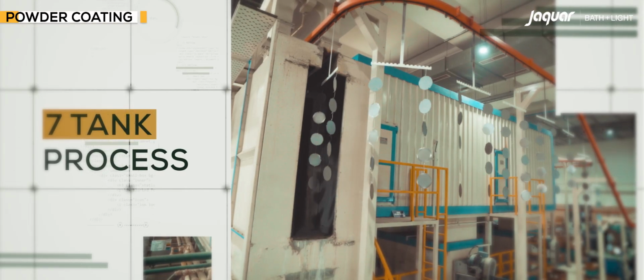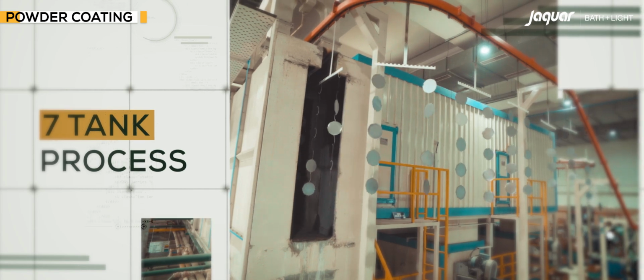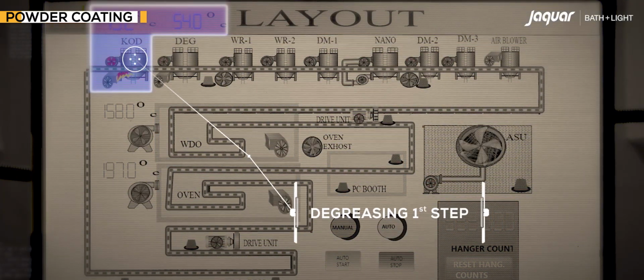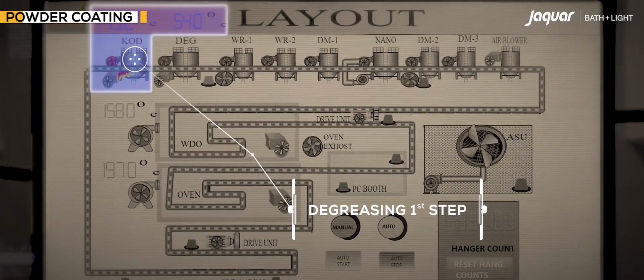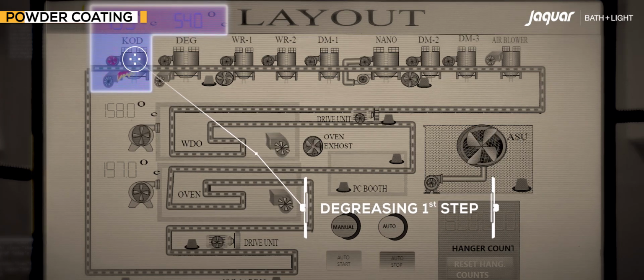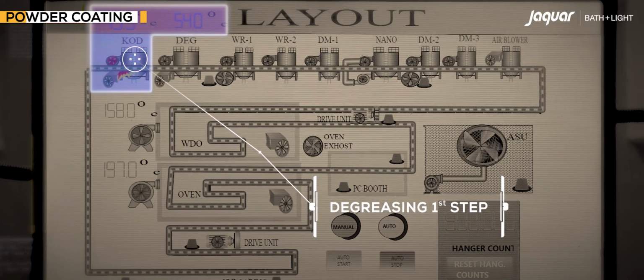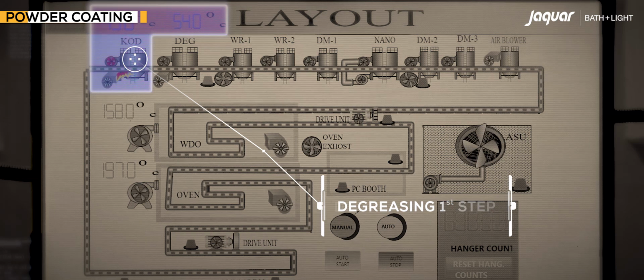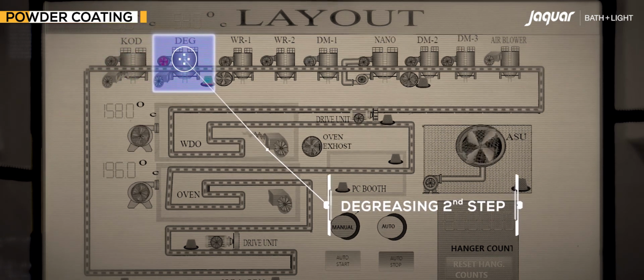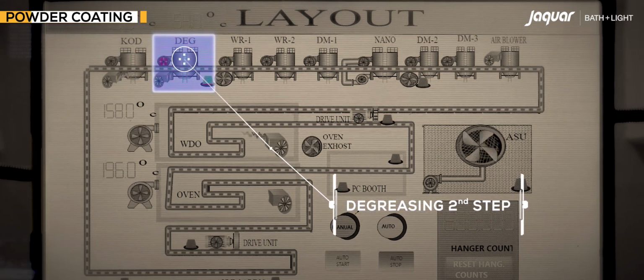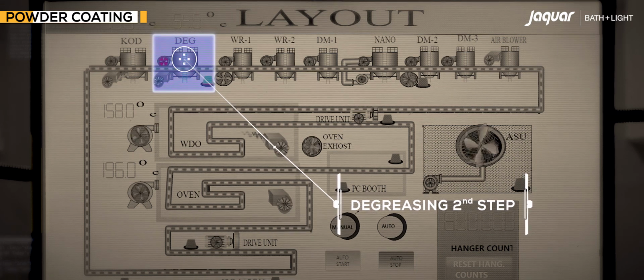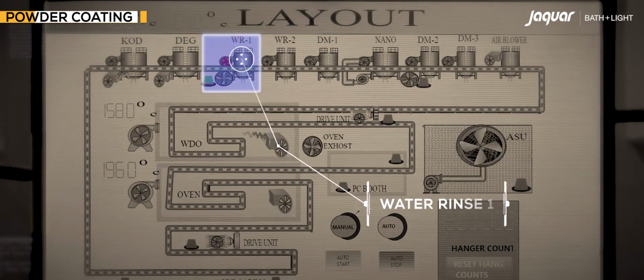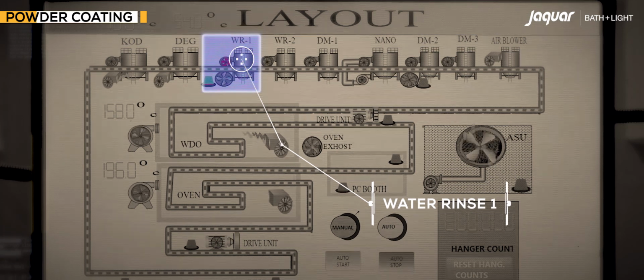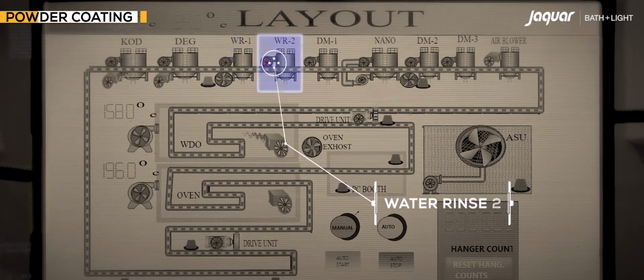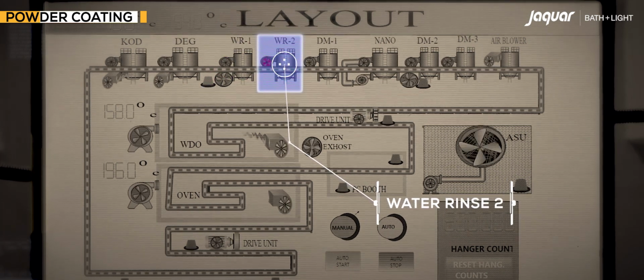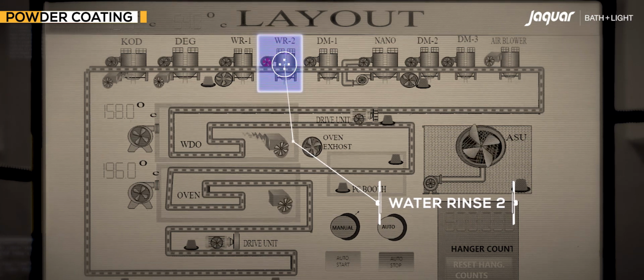Now comes the 7-tank process. In the degreasing first step, heated chemicals at 45 to 50 degrees in the caustic base are sprayed on the housing through nozzles to get rid of oil, grease, etc. In degreasing second step, the same process is repeated to ensure no oil or grease is left. Then, water rinse 1 takes place to remove any chemical from the surface. Water rinse 2 is the repeat process to ensure no chemicals remain on the surface.